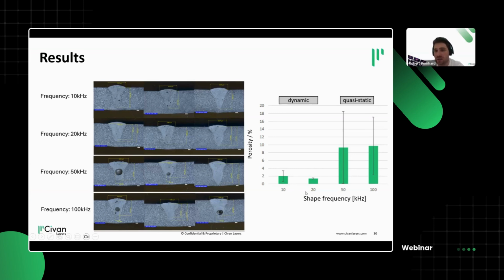But if you find this sweet spot in welding shape frequency, which you can easily do with our laser, doing some frequency sweeps, you get into a region where there is, let's say here in this example, 20 kilohertz, a very well behaved weld seam. Not much porosity, or at least in-spec porosity. This is here below 2%.